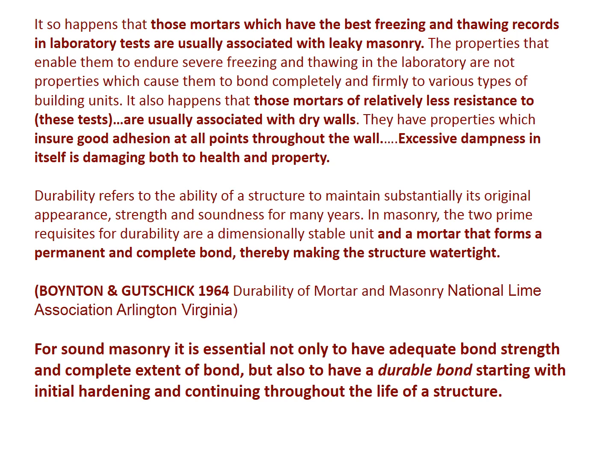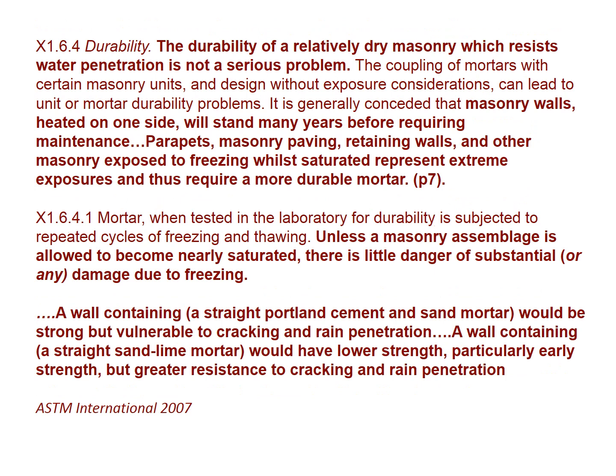So long as the bond is complete and even throughout and is of good extent, water will not enter the fabric of that building to any significant extent. And if that mortar is porous, any moisture that is absorbed will be quickly sent away by the action of wind and by capillarity. For sound masonry, it is essential not only to have adequate, not necessarily strong, bond strength and complete extent of bond, but also to have a durable bond starting with initial hardening and continuing throughout the life of a structure, not shrinking away later.